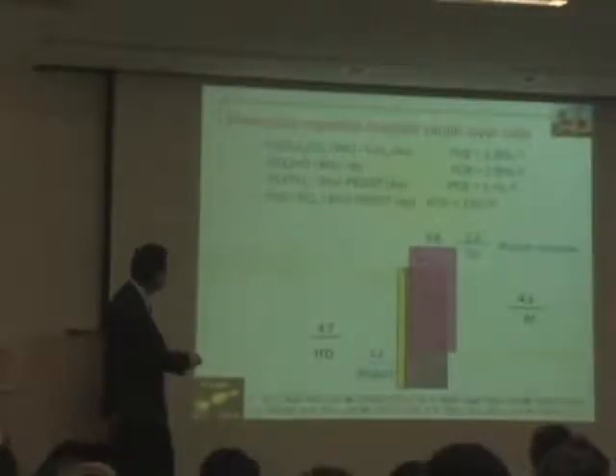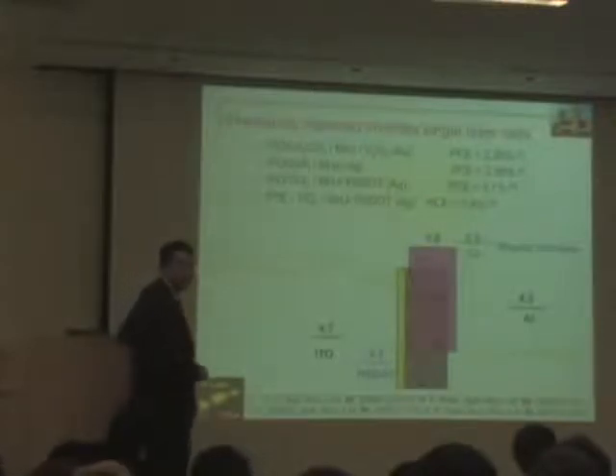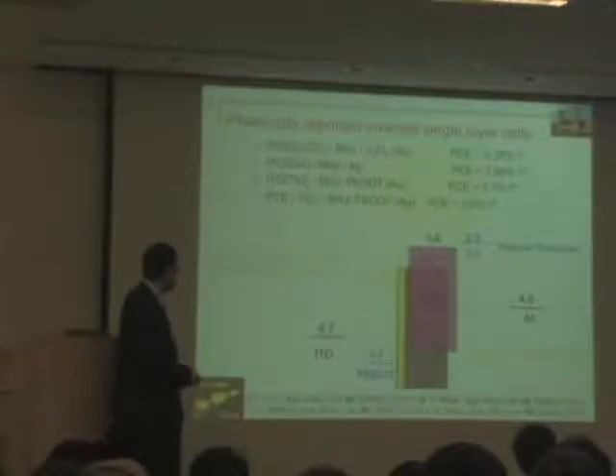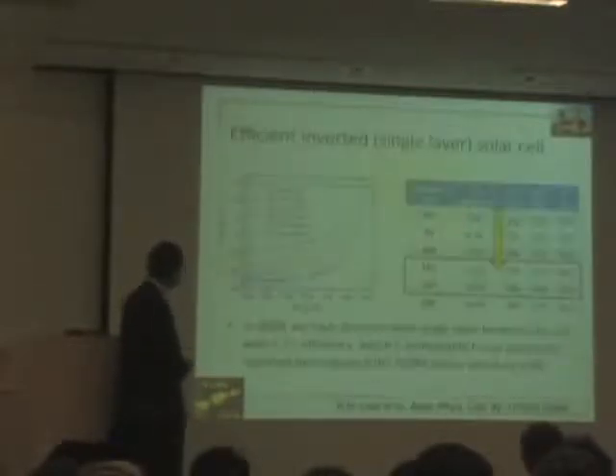So this paper we published in 2006 by Dr. Gang Li turned out to be the first inverted polymer solar cell publication. And then later, NREL and then Konarka all followed the same trend, which I believe they came out with the idea independently because the publications are very close. Okay, so slowly we make our single layer inverted structure better.